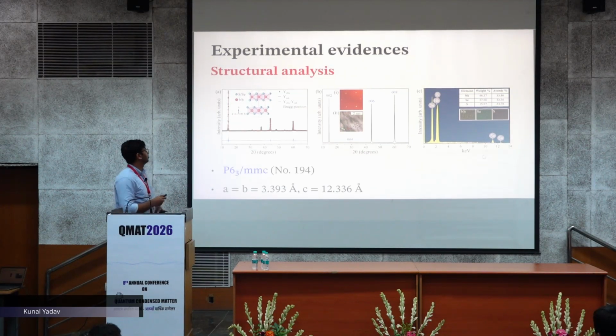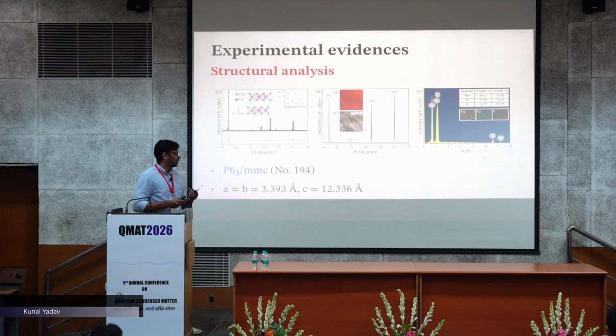So we come to the experimental evidence. We have made single crystals of NbSeS, and we have done powder XRD on the NbSeS, and we find that the structure is almost retained, and the structure is P63/mmc, which is number 194. This means that sulfur and selenium have 50% occupancy here, and also the EDX shows the weightage of selenium and sulfur is around 50-50.